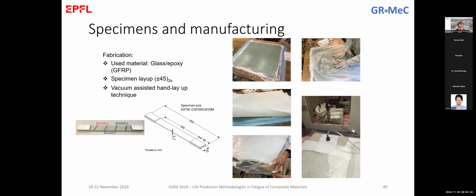And then we used some techniques for the measurement of the strain with a video extensometer. So the video extensometer is similar to what you know today as DIC, but it only measures specific points. It does not give full field measurements, but I would say that it resembles more a clip gauge. You have 2 points, and then you measure with the photos the relative distance of these 2 points or 2 lines that you have in this case. Why did we do this? You see in this photo, we say measurement 1, measurement 2, and measurement 3. The reason was that we wanted to have, first of all, the overall strain of the specimen, but also the local strains of the specimen, to be able to correlate this to the damage that was observed.